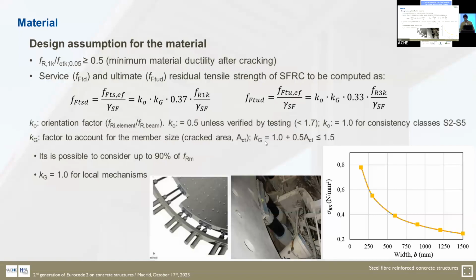The size effect factor is a corrective factor for taking into account that the variability of the residual strength reduces with the cracked area. It is assumed, or this formulation can be used, where the area is ACT, the area of the cracked region, and never superior to 1.5, because if we take values superior to 1.5, we can clash with the statistics, and we can end up with values of FRK superior to the average, right?